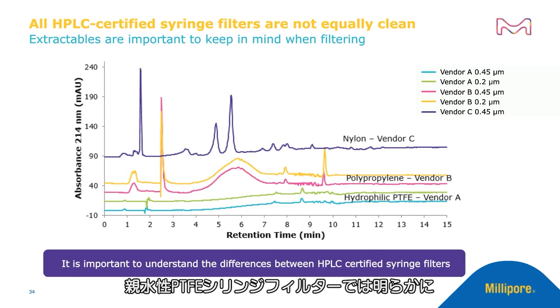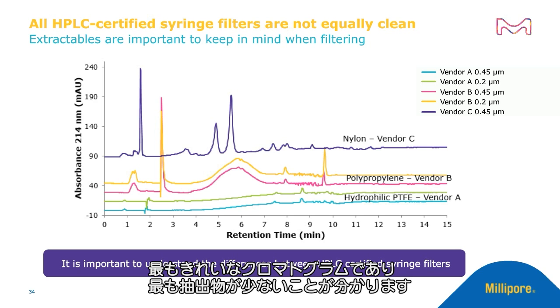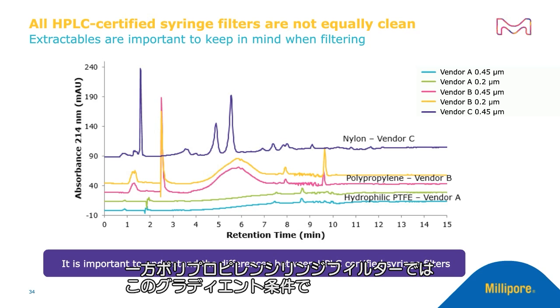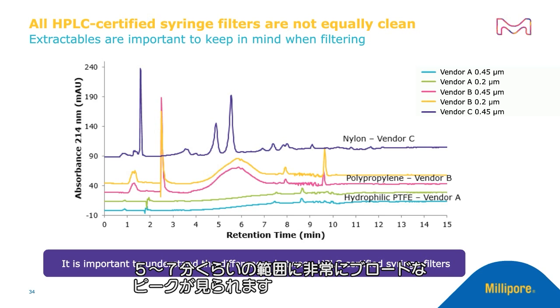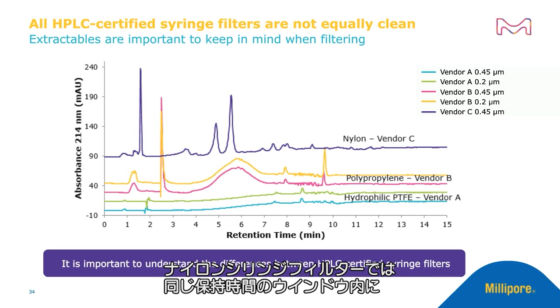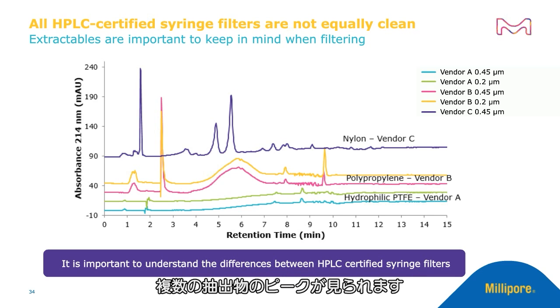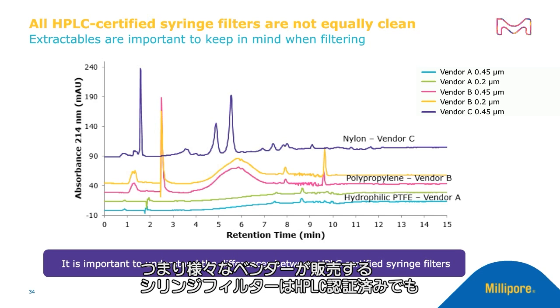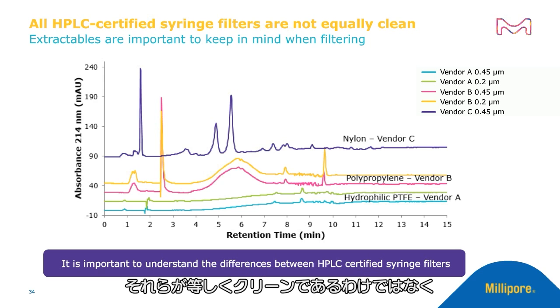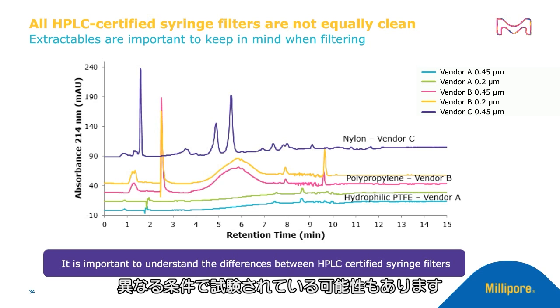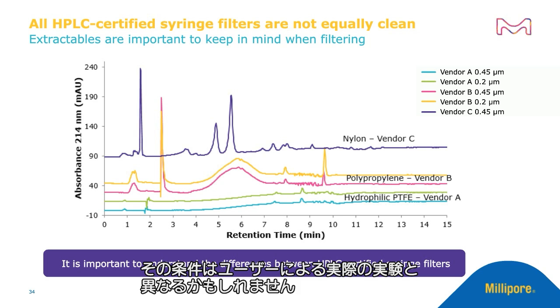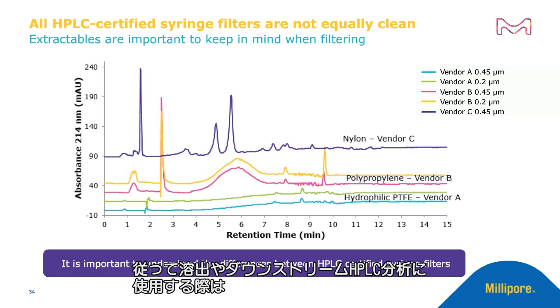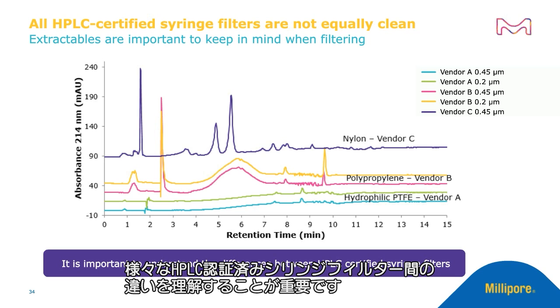As you can clearly see, the hydrophilic PTFE syringe filters have the least amount of extractables as seen by the cleanest chromatogram, whereas the polypropylene syringe filter shows a very broad peak somewhere in the range of 5 to 7 minutes within this gradient, and the nylon syringe filter shows multiple extractable peaks within the same retention time window. So even though HPLC certified syringe filters are available in the market from various vendors, they may not be equally clean, and they may be tested under different conditions, which may be different than actual experimental work that you might be doing. So it is important to understand the difference between various HPLC certified syringe filters when it comes to using those for dissolution and the downstream HPLC analysis.